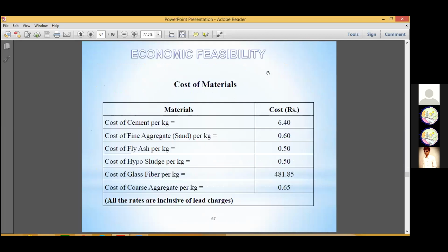The cost economic feasibility regarding the cost of materials: the cement at that time was 6.4 rupees per kg, fine aggregate 0.6 rupees per kg, fly ash 0.5, 50 paisa per kg, hyposludge also 50 paisa per kg, glass fiber 481 rupees per kg, coarse aggregate 0.65 rupees per kg, including lead charges. This is regarding the cost of materials rate.